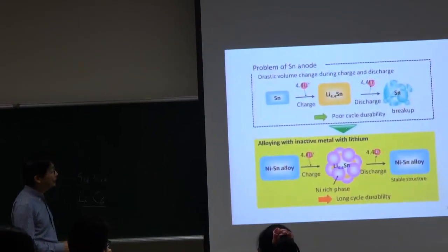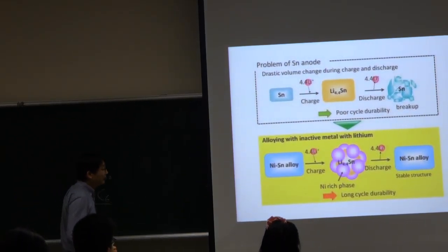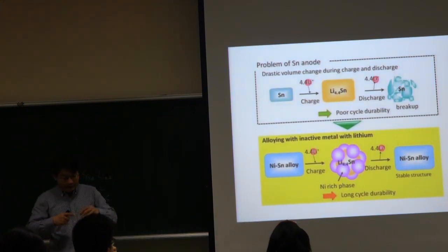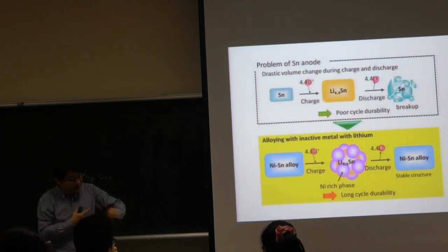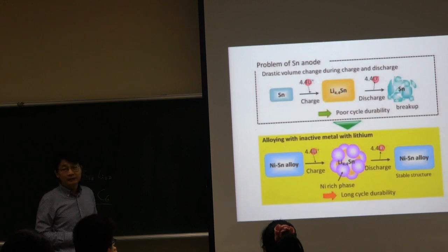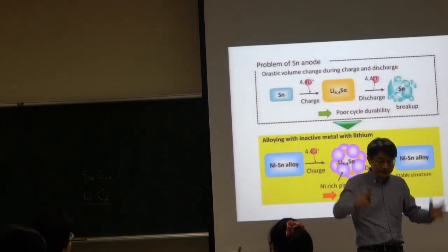But unfortunately, during charge and discharge, tin is quite soft. Charging means lithium insertion, right? Insertion and then extraction again, which makes the mechanical property degrade, and therefore it will break. When the tin breaks, you will see the battery expand.